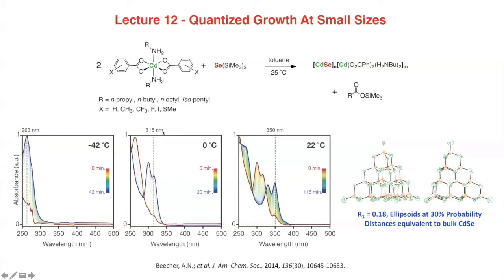And so what you're watching in this case here is an Ostwald ripening process where these clusters, or whatever this is, are dissolving, and this new cluster is precipitating. And again, at minus 42, or at room temperature, this cluster dissolves, and this one precipitates or grows. So all you've done is converted 10 millimoles, or whatever the scale is on which he ran the reaction, from one cluster size to the next without adding any new material. So it's just rearranging and heading downhill.